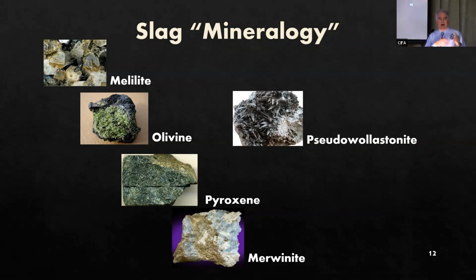But if you allow that slag to cool a little bit slower, then you can start to grow crystals once the temperature of the slag drops below 2,640 degrees Fahrenheit for most compositions of slag. And then if it cools even slower, well, those crystals can grow larger and new crystals can form, again, depending on the chill rate and the composition of the slags. But again, most slags cool faster, so they don't really grow large crystals. And slags from furnaces that are fueled using cold blast charcoal typically produce higher silica or more glassy slags, whereas hot blast furnaces that use coal or coke as the fuel typically don't produce those glassy slags. And that's exactly what we see in Cornwall, and we'll talk about that more later in the presentation.